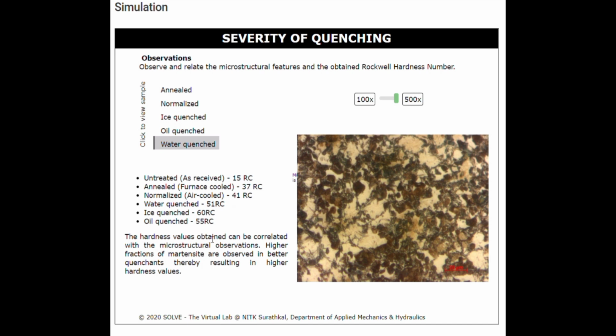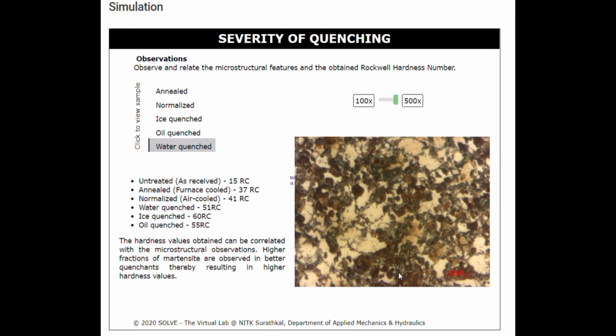The hardness obtained can be correlated with the microstructure observation. Higher fractions of martensite are observed in better quenchants, thereby resulting in higher hardness value. You can see it's 20 micrometer. That's all from me.